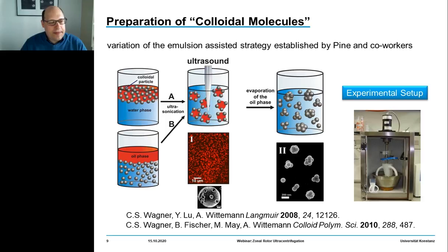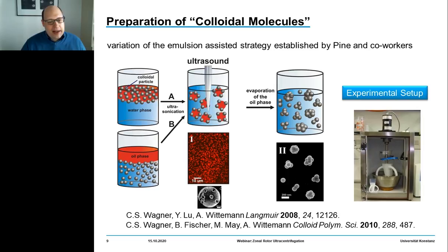To make these colloidal molecules, we basically mix oil and water and add the particles to be assembled into clusters to one of the two fluid phases. After emulsification — performed by powerful ultrasound — they will be trapped to the surface of the emulsion droplets.